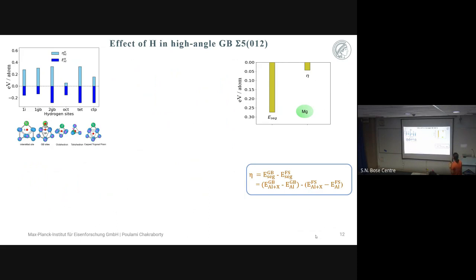let us focus first on these two plots. This plot shows that there is no hydrogen in the system and only magnesium is present, and we can see the segregation energy is negative. This negative segregation energy basically translates into this, that magnesium in the aluminium sample. Yes, there is a minus on the axis. Sorry, I'm very sorry. Thank you for pointing it out. The segregation energy of magnesium is negative,